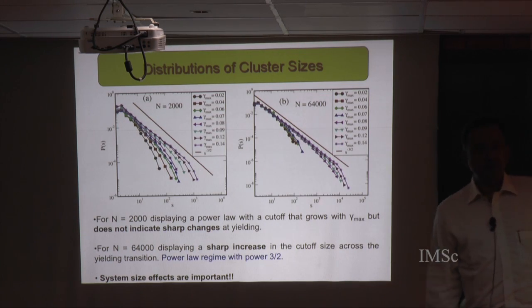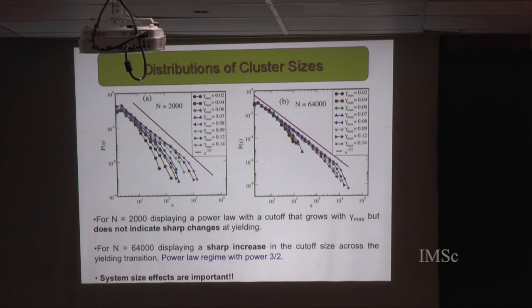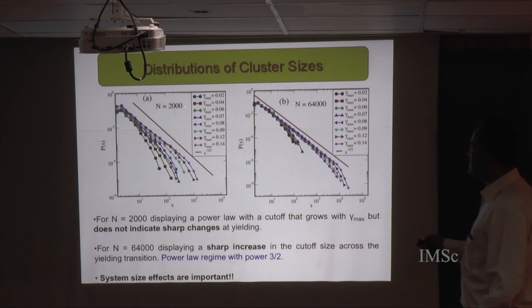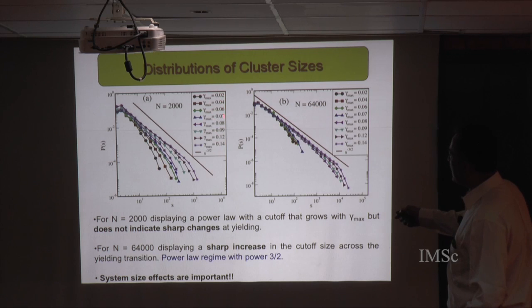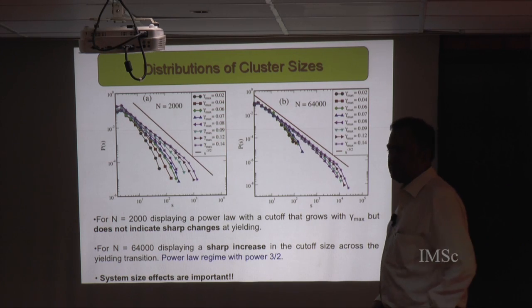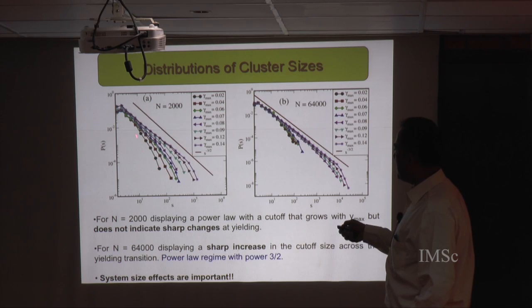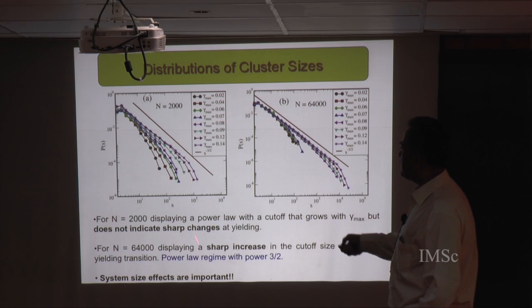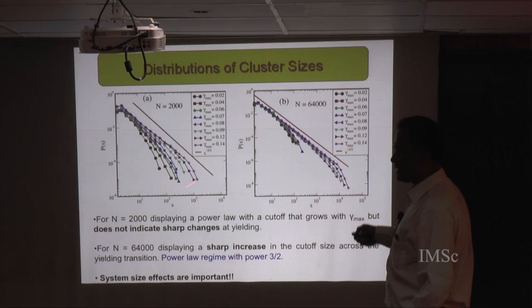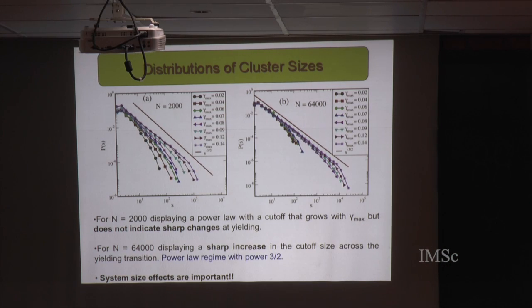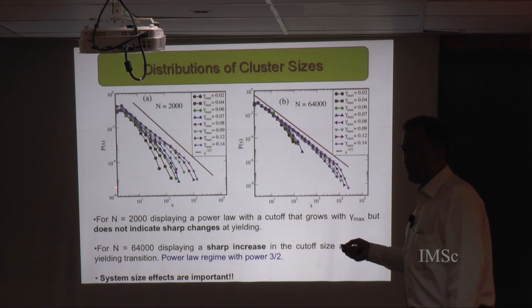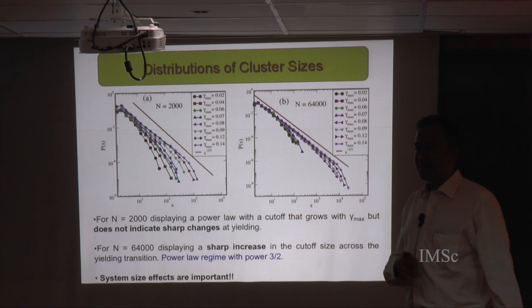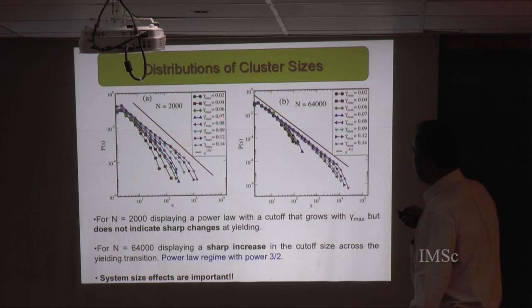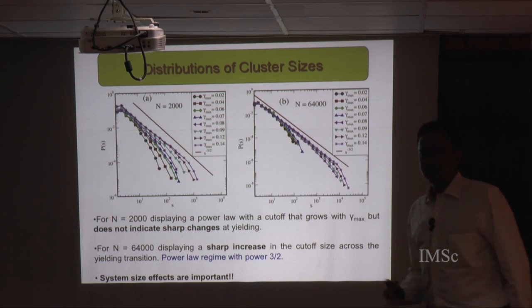Then we look at the distributions of the sizes of clusters formed by these particles. Here is this avalanche size distribution as a function of size for a range of amplitudes of deformation. As you increase the amplitude of deformation, there's a power law regime followed by a cutoff, and this cutoff moves to larger and larger values, which is good—this is what you expect. But it shows no indication of crossing what I've so far described as a sharp transition. Between 0.07 and 0.08, I should see some difference in behavior, and I don't see it.